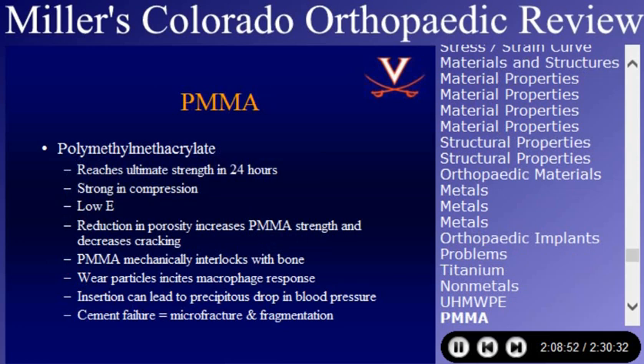Things you need to know about PMMA from a biomechanics standpoint. It reaches its ultimate strength in 24 hours, so it's not completely hard. It's, just a few minutes after you insert it. It's strong in compression. It's poor in tension. It has a very low modulus of elasticity. I know you already know that the different generation techniques of cementing, reduction in porosity increases PMMA strength and decreases cracking. It mechanically interlocks with bone. It's not an adhesive. It's more of a grout. Wear particles can incite a macrophage response. Again, insertion can lead to a precipitous drop in blood pressure because of an anaphylactic reaction to the monomer. If those of you have been involved with that, it is a very scary situation. Cement failure occurs from microfracture and fragmentation.